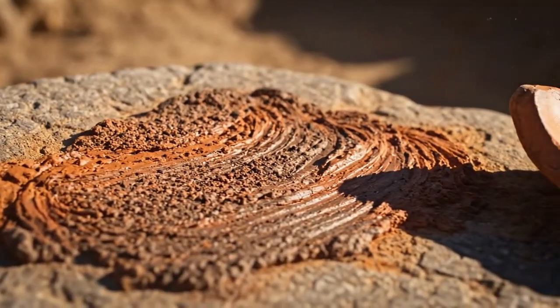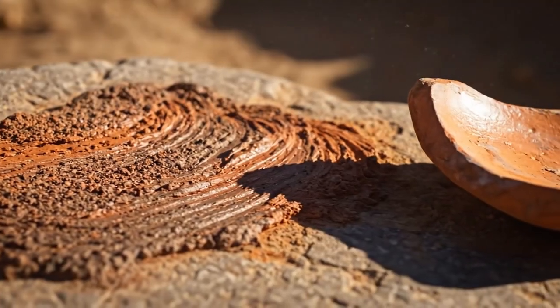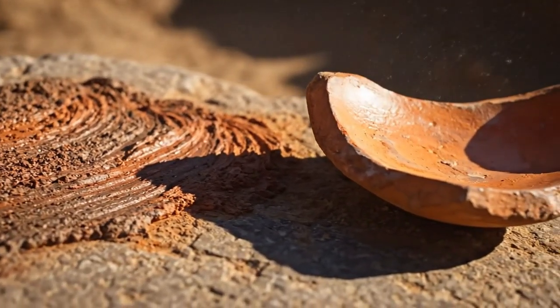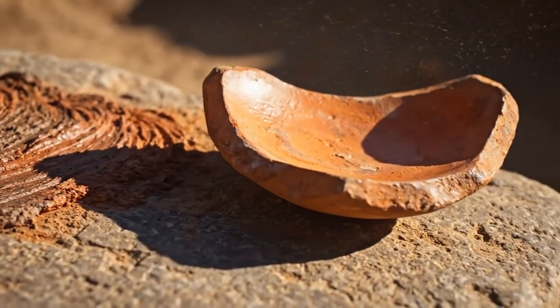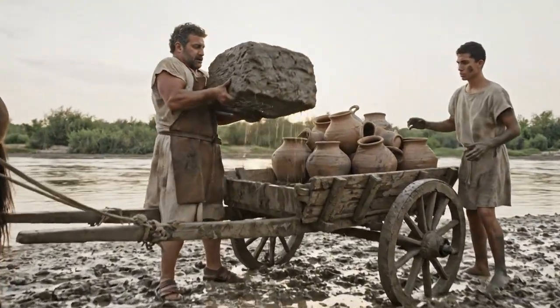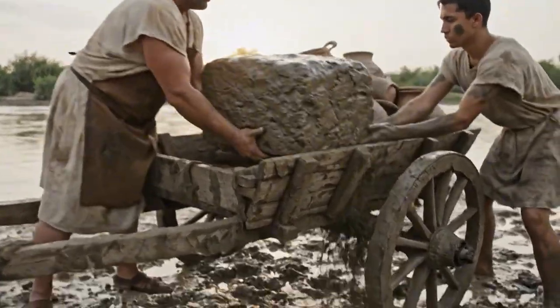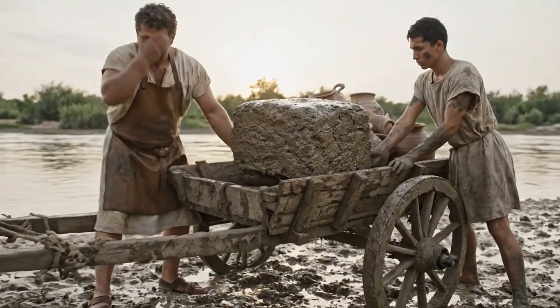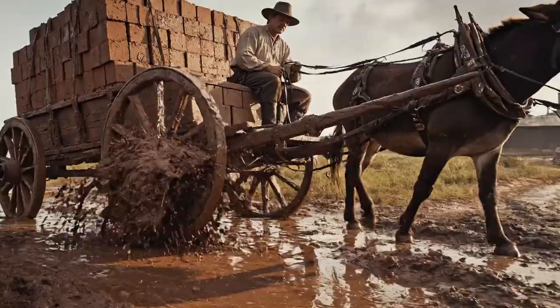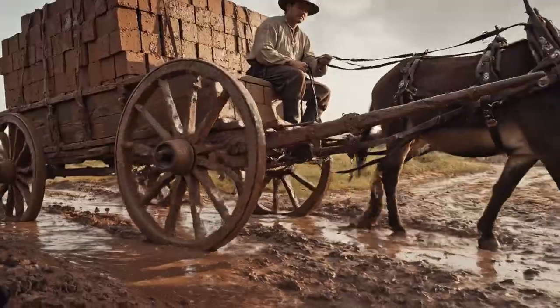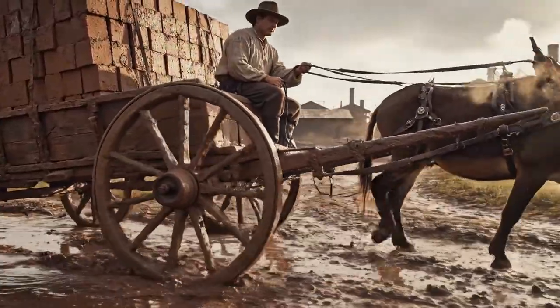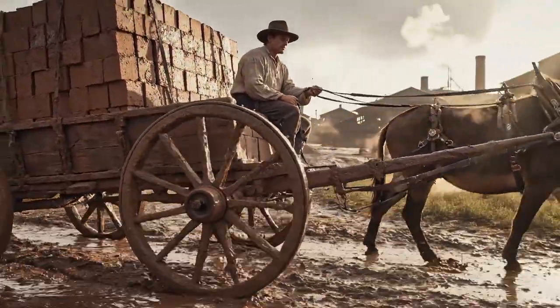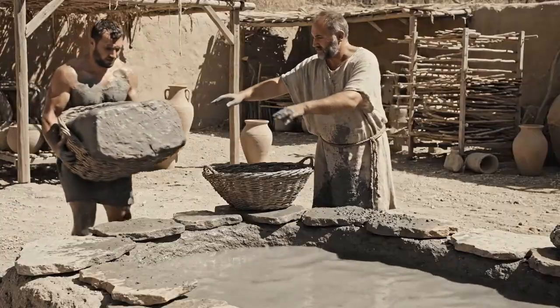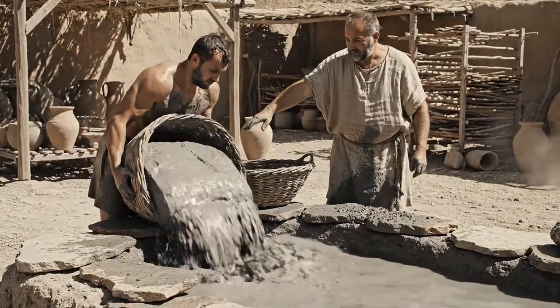The ideal clay for Roman lamp production is an illitic clay, rich in iron oxides, which will fire to a warm reddish-orange and sinter into a dense, low-porosity body, somewhere between 700 and 900 degrees. Workers extract this clay in heavy dripping blocks, pile it onto mule-drawn carts, and haul it back to the workshop, where the real preparation begins.